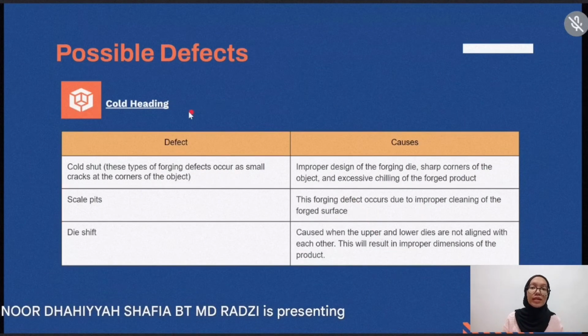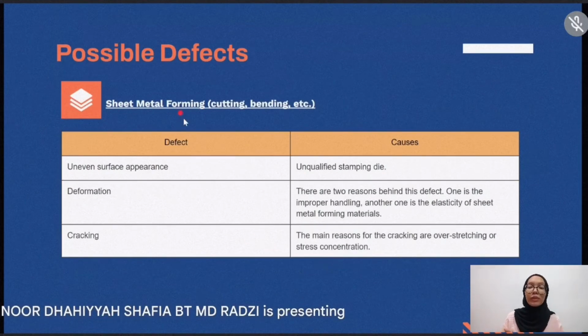In the cold heading process, the defects include cold shut, which is caused by improper design of the forging die. Scale pits happen due to improper cleaning of the forged surface. Die shift happens when the upper and lower dies are not aligned with each other. Lastly, in the sheet metal forming process, which includes cutting, bending, and so on, the defects include uneven surface appearance, caused by an unqualified stamping die. Deformation happens due to two reasons: firstly, improper handling, and secondly, the elasticity of the sheet metal itself. Cracking happens due to overstretching or stress concentration.